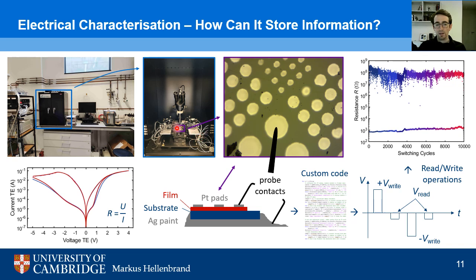So now by applying a voltage to this top electrode here, we can measure the IV curve that I explained before. So we have the current through the device as a function of the voltage, and by applying a positive voltage, we distribute the oxygen vacancies on one side of the device, which gives us a certain current level, and by reversing the voltage, we move them back from the interface and we get the other resistance state. So again, our binary states 1 and 2.